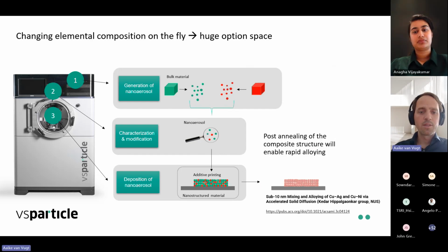Last, the example that John also showed. If you use 2 sources, 2 G1s in the printer, one source can process material that is green, the other one can process the red material into nanoparticles. Both nanoparticle streams are then combined into a single stream, and that is then being printed. So what you print is a nanoporous layer that is built up of green nanoparticles and red nanoparticles. But the nice thing about the fact that those particles are so small, 2-3 nanometer in size, is that they have very fast alloying kinetics, again, if the material will form an alloy. So at post-annealing, you could make this composite material into an alloyed material because you will form rapid alloys with these very small nanoparticles.